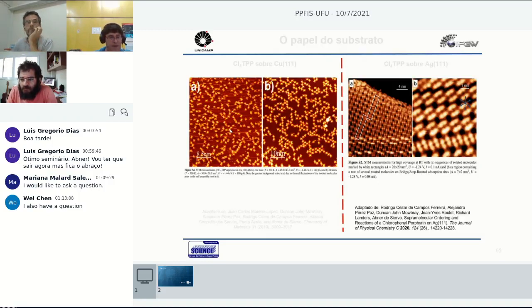Yeah, also. In this case, for example, if you try to measure, the only chance is that you need to freeze. For other molecules, we have this nitrogen, they bind to the surface, they freeze. And because of that, we can measure without disturbing with the tip. Because typically you do STM at low temperature. Our equipment, we are doing STM at room temperature. And we can do it at room temperature for some systems where we have this strong interaction. Otherwise, we have no chance to see the individuals.